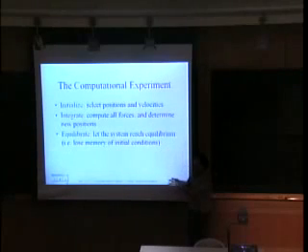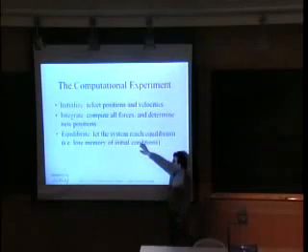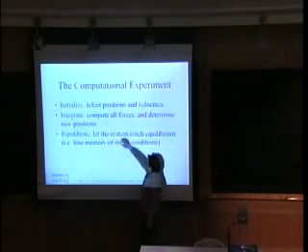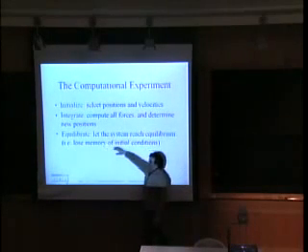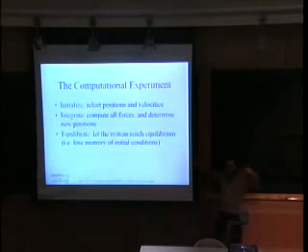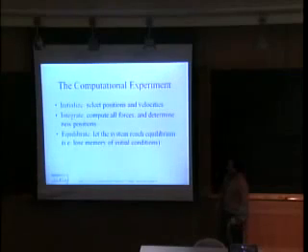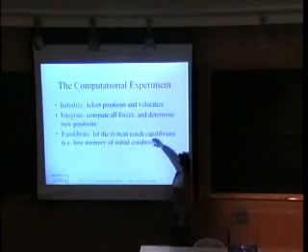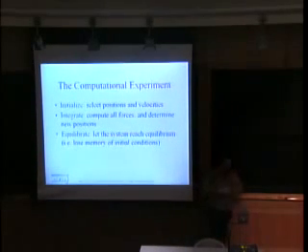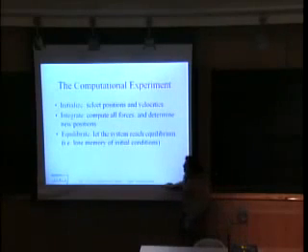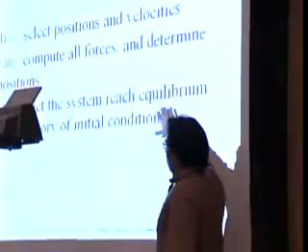Well, we had liquid silicon, we have cooled it down. In a way, what's happening is that we are never equilibrating it because the system goes into a glass phase, and so it never loses memory of its initial condition. It's always trapped in this pseudo-liquid, now glassy state, while in reality, at a temperature below the freezing or the melting point, equilibrium would be given by a crystalline state with the ions vibrating. So there are cases in which equilibration is so difficult that we actually never reach it. Silicon never goes to a crystal, and that's why we need to be careful. But in most cases, hopefully, we are lucky and we lose memory of the initial condition.